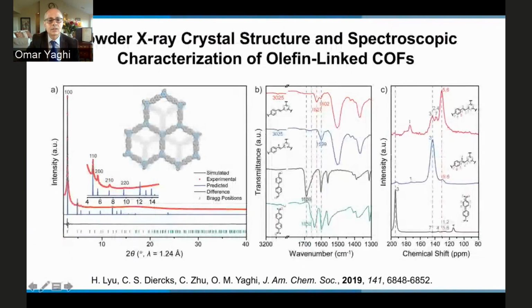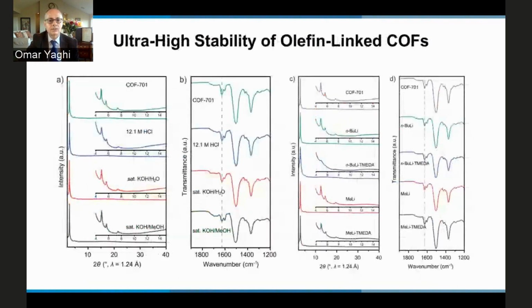The structure looks like this. It's a slipped graphite layered structure. And as we did before, we look at the IR and NMR, both carbon-13 and nitrogen-15 NMR, to characterize the connectivity, and we use X-ray powder diffraction to confirm the structure.